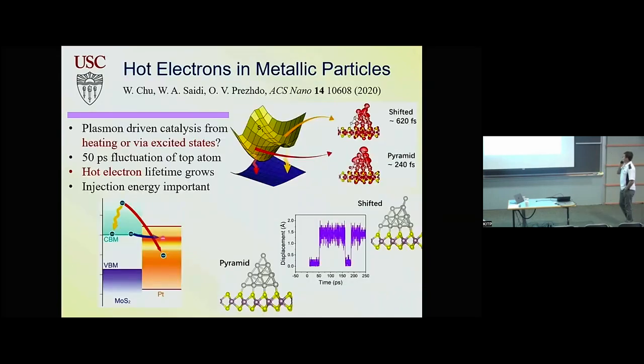So now a question about photocatalysis or lifetime of states in plasmonic systems, and in general in nanoscale systems: you really have to sample configurations. What you learn if you do just one configuration, some optimized structure, may not represent reality, what happens at room temperature and on longer time scales. So in this case, we developed a machine learning force field. This is a real system that people studied experimentally, where you have a platinum cluster on the surface, and it could be used for plasmonic applications, could be used for photocatalysis.